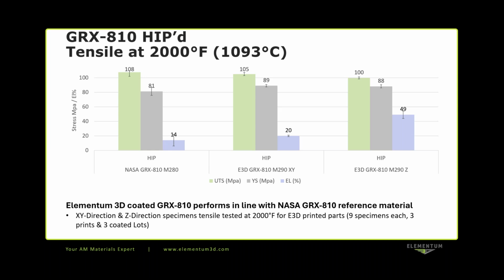So this is exactly what we wanted to demonstrate, that the commercial scaled coating and production processes are matching the great NASA data that Tim shared. So X, Y direction specimens as well as Z direction specimens were tested in tensile at 2000 degrees Fahrenheit for the Elementum 3D printed parts, looking again at a limited data set here of 9 specimens each, consisting of 3 different builds and 3 different coated lots of materials.